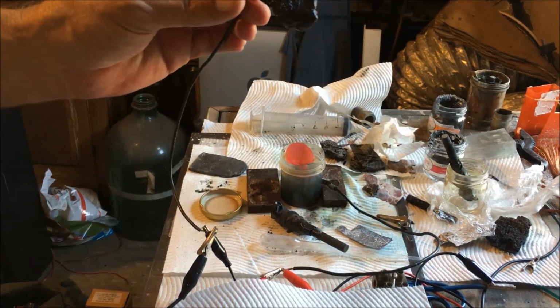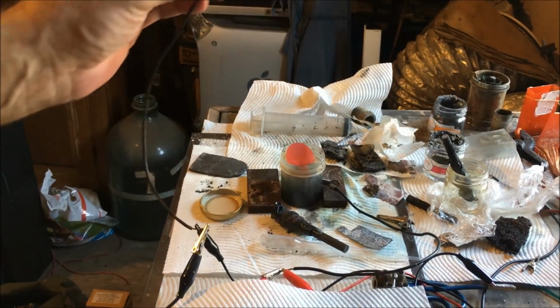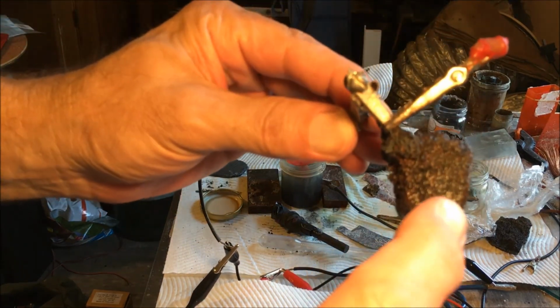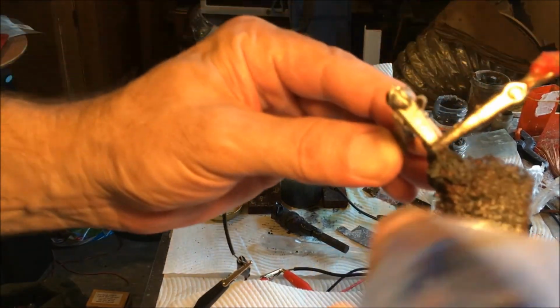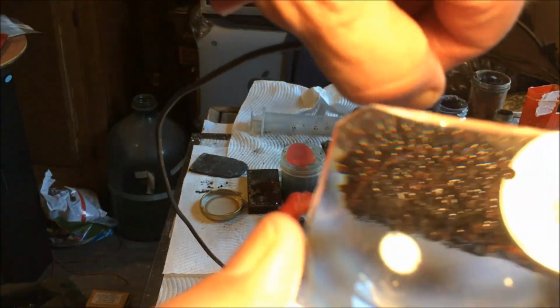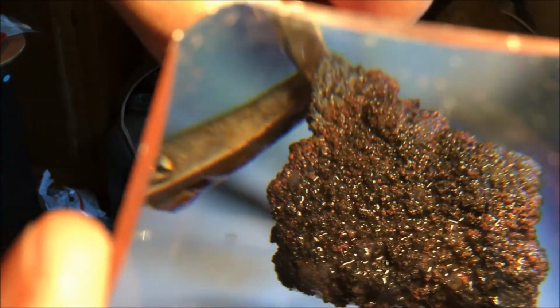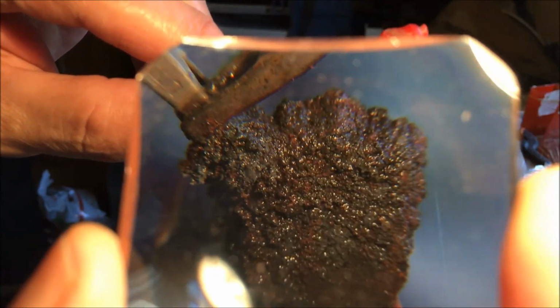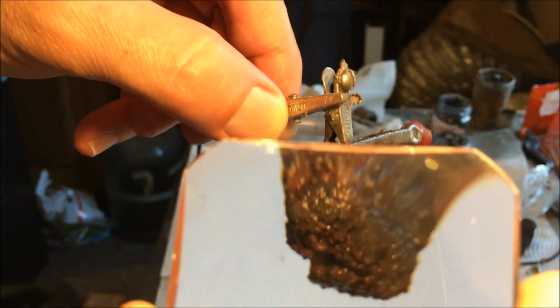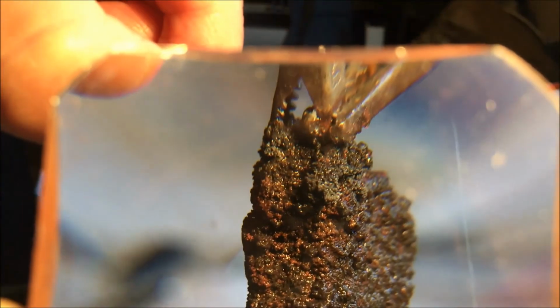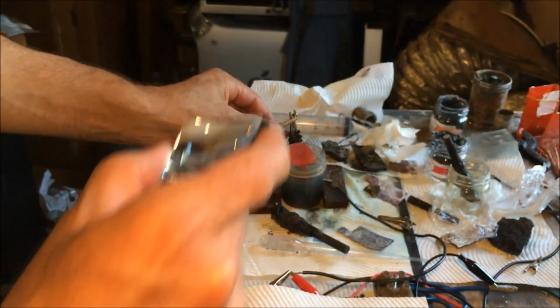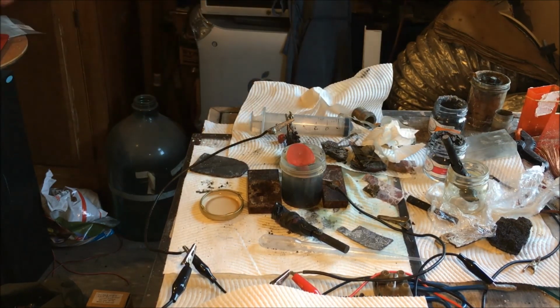So for the carbon cell, it's sort of somewhat lost all of its pores. That's the side that was facing it, and the non-facing side is still lumpy and holey. But see the copper plating also all around it? The copper comes when it's discharging and the zinc plates over the top of the copper, I think, on a charge, which is maybe hindering it. Alright, I'll swap electrodes and give it an hour's charge and see if we get a better graph.